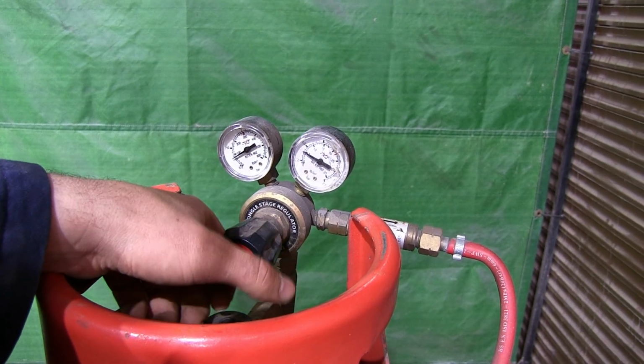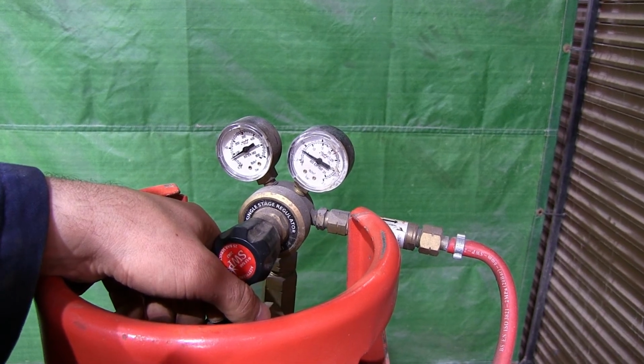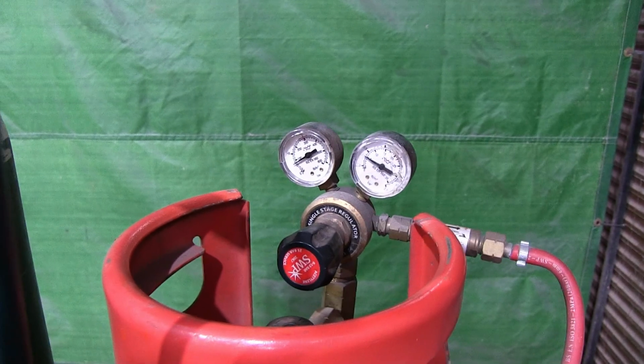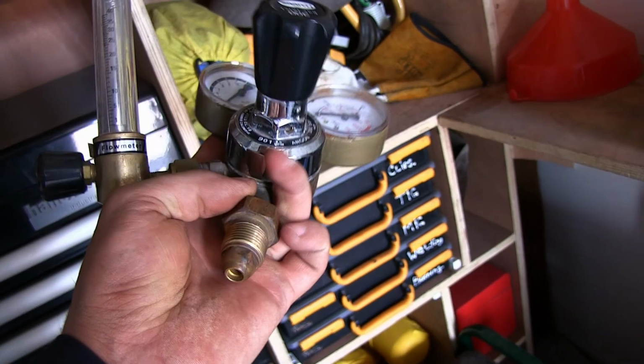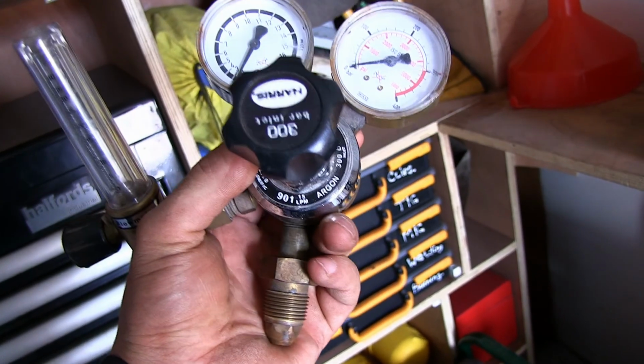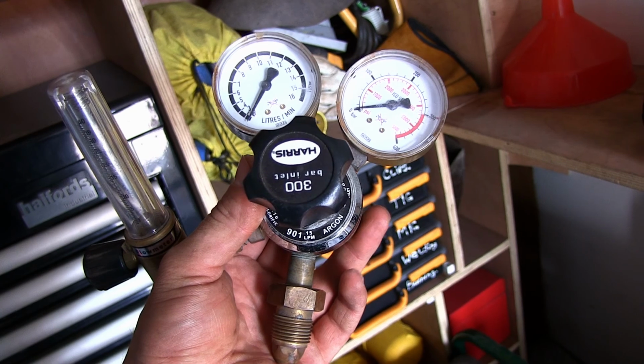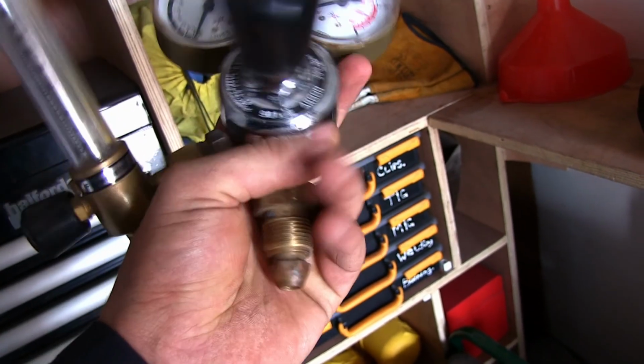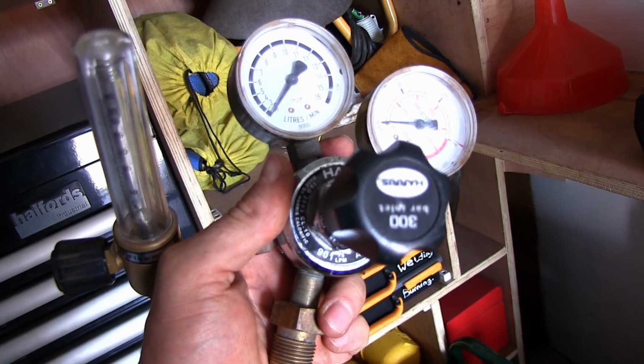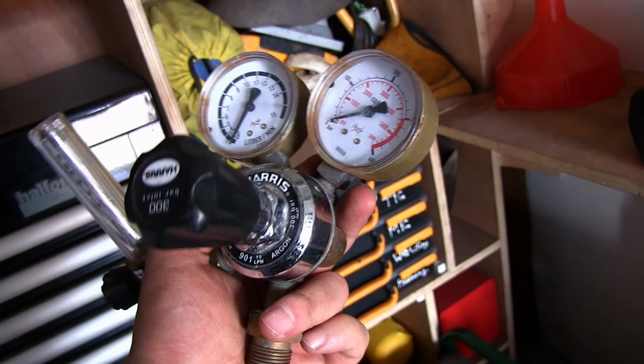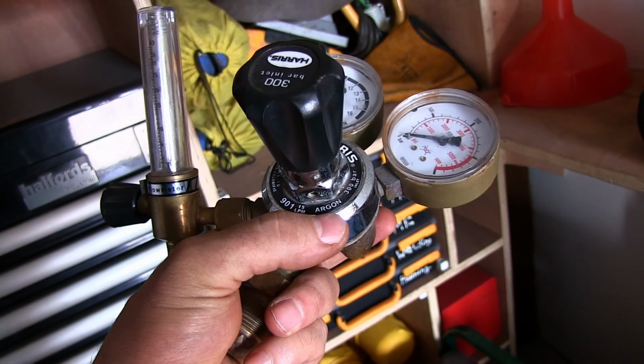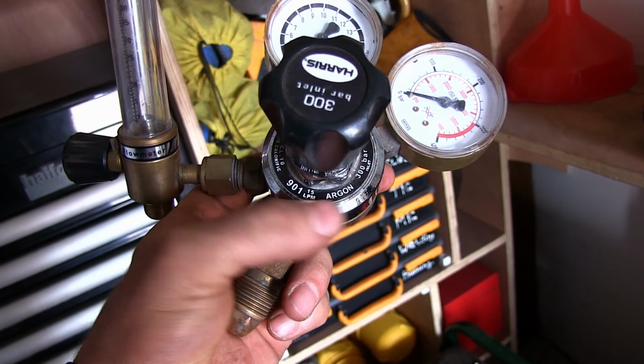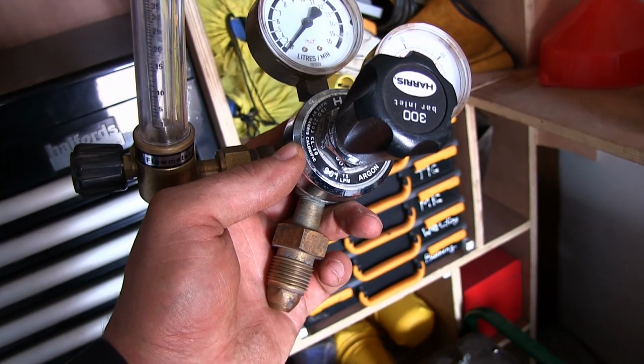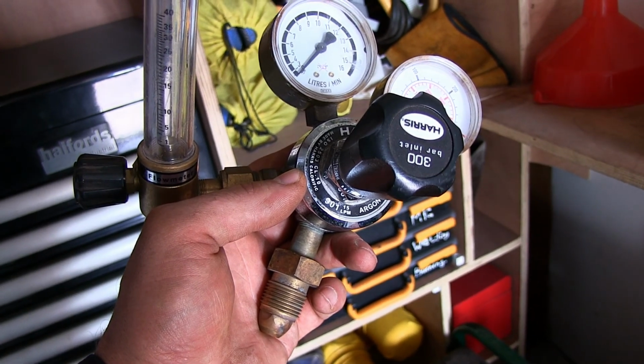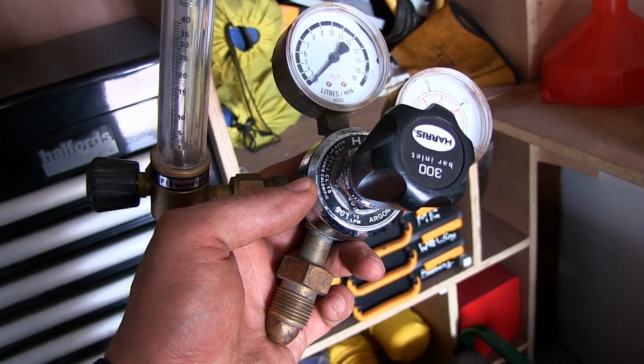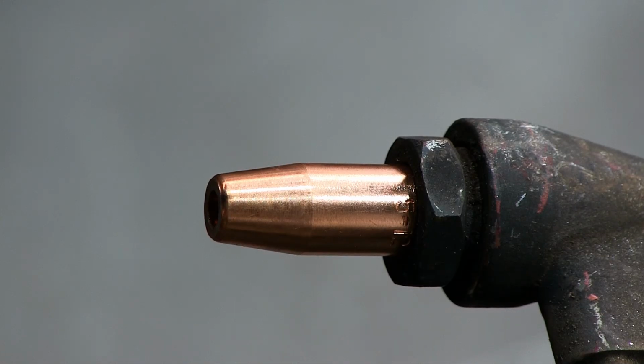I also have to say that older type gauges, similar to what you see on the propane, can be mounted on any bottle like argon or CO2, and also an oxygen bottle. But the systems that compress argon, CO2 and nitrogen don't work to the same purity as oxygen compression systems. So if you use the same gauge on argon or any other gas and then put it on an oxygen bottle, it may have some oil particles in it. When you put it on an oxygen bottle and turn it on, the gauge can explode. It's a horrendous experience, and nobody wants to see gauge pieces going through their mind in the last moment. So you really need to pay attention to that, otherwise you may find yourself in deep trouble.